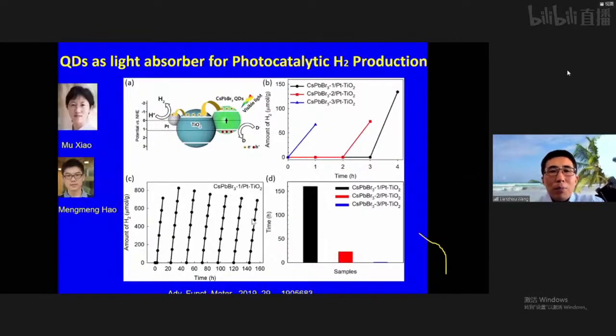And by using the same idea, we tried to introduce the quantum dots, the perovskite quantum dots, into the photocatalytic system. In this case, we also have a good engineering of the surface ligand of the quantum dots, which on one side can protect the quantum dots from decomposition. On the other side, it will not block the charge transfer between the quantum dots and the TiO2 in this case, and which